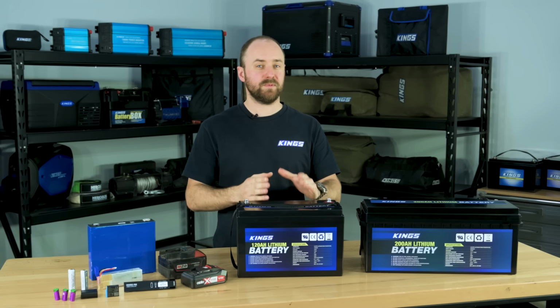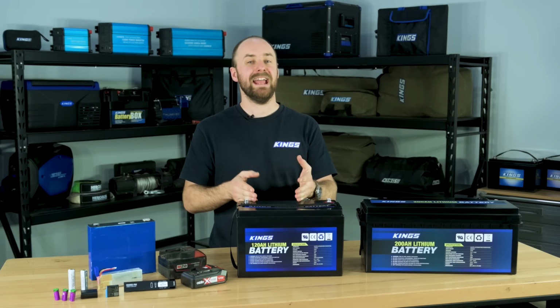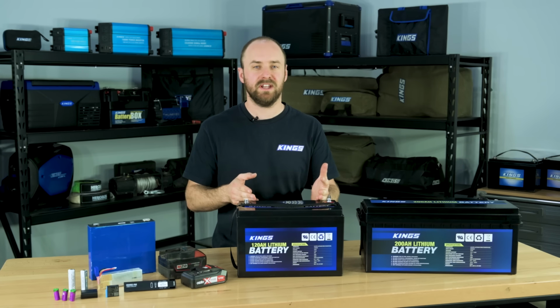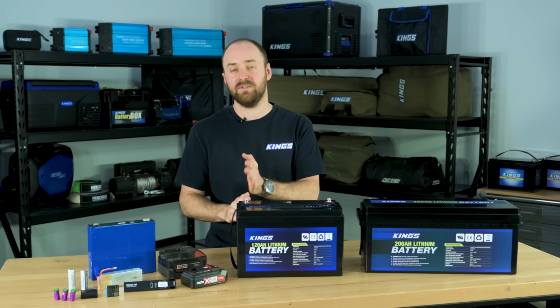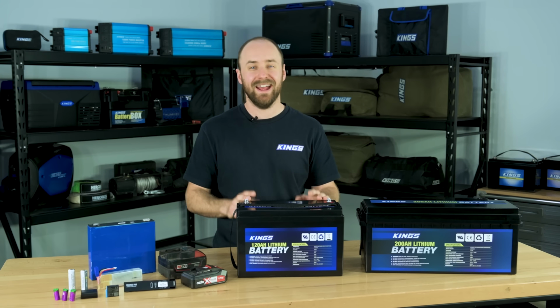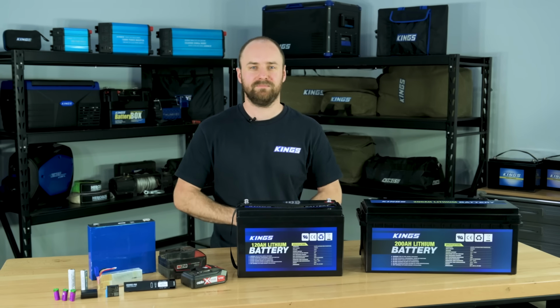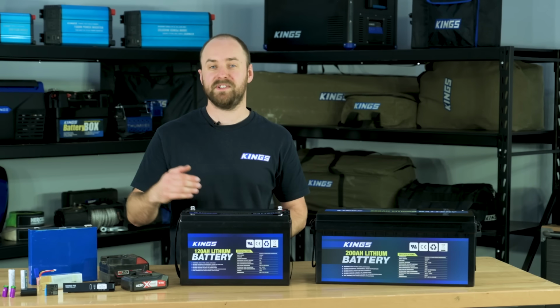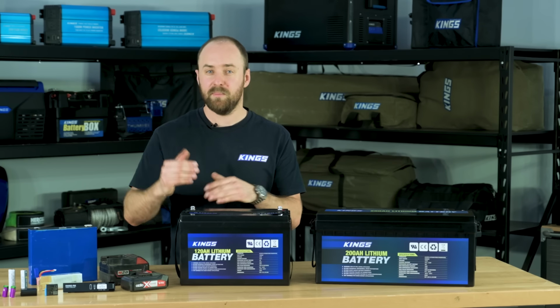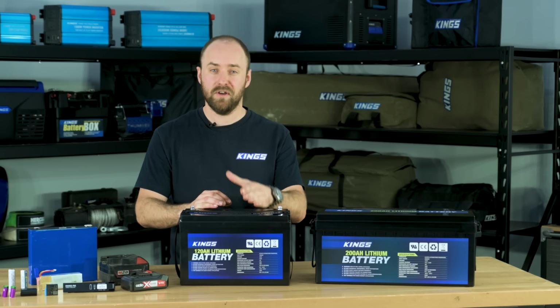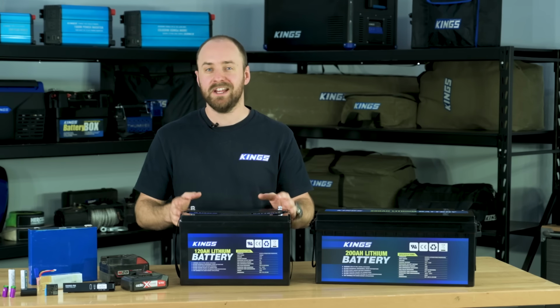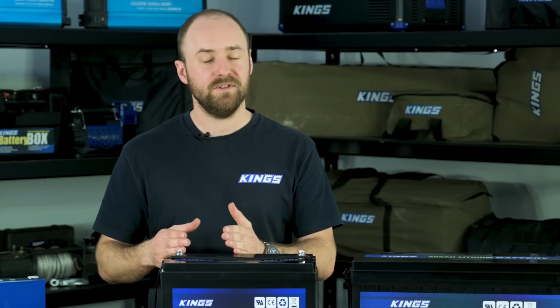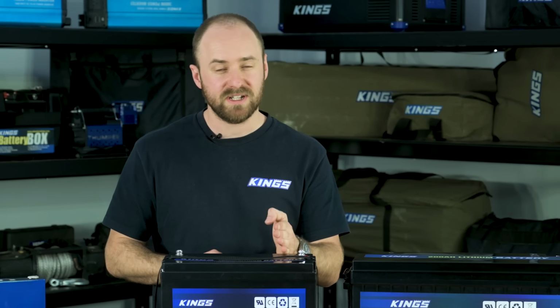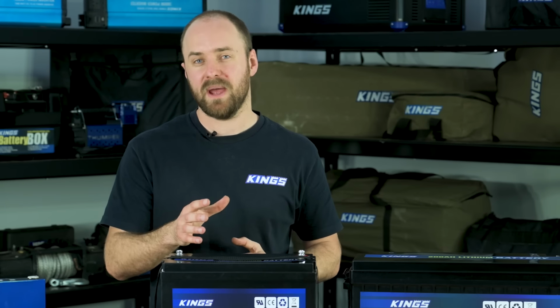Now that you've ensured your battery's warm, but not too warm, you've got to decide how much of the actual percentage you want to use. Now you can use these batteries all the way from 100% down to 0%, and that will get you around 2,000 cycles. If you decided to only use this battery from say 90% down to 10%, meaning you're using 80% or 96 amp hours of its overall capacity, you could do it up to 4,000 times. And if you want it to be really safe and only use your battery between about 75 and 25%, getting you around half the capacity, you could use your battery 8,000 times.